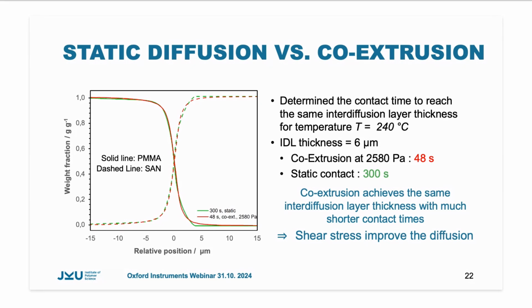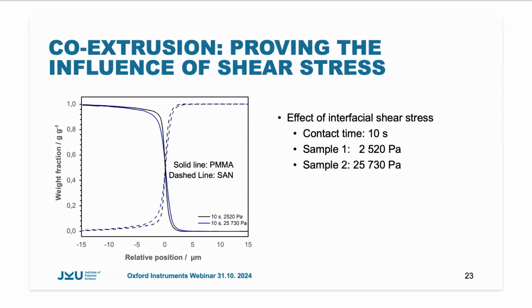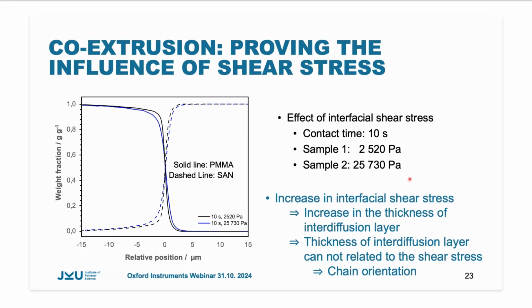But what is the regime of this impact? Therefore, we perform also an experiment where we increase the applied shear stress and have the contact time constant. So have the contact time constant, increasing the shear stress by a factor of 10. What we see is there is an increase in the interdiffusion layer thickness, but this increase is not related to the same amount as the shear stress is increased. This gives us the first hint that there's also an influence of the chain orientation into the interface formation.